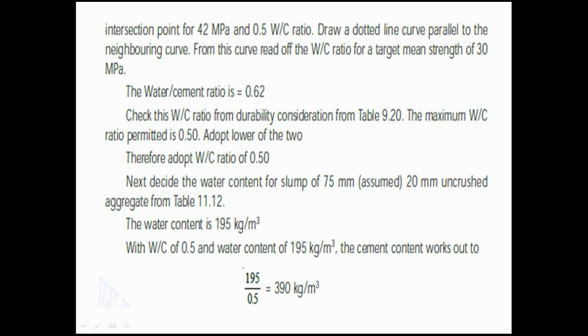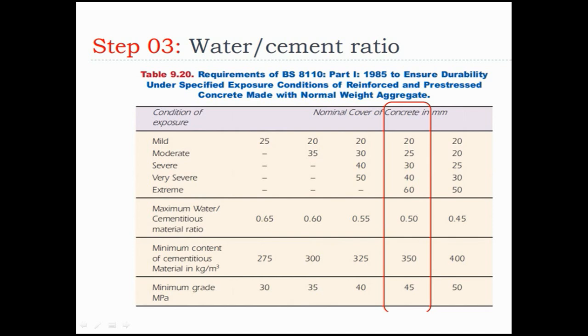Check this water-cement ratio from the durability consideration table 9.20. The maximum water-cement ratio permitted is 0.50. We adopt the lower of these two values. This is the durability table — for moderate exposure condition and 25 mm cover, the maximum water-cement ratio given is 0.5, and the minimum cement content is 350 kg/m³. In case of water-cement ratio, we take the minimum value out of the two — so out of 0.62 and 0.5, we adopt 0.5.